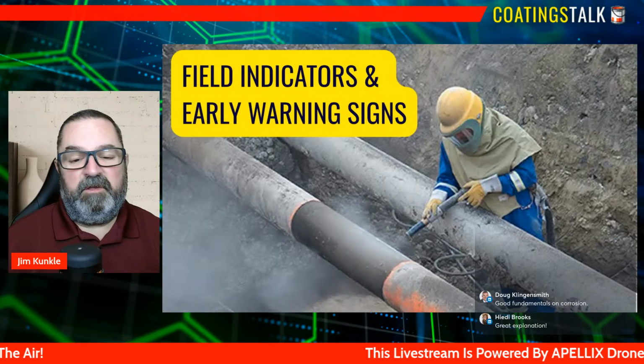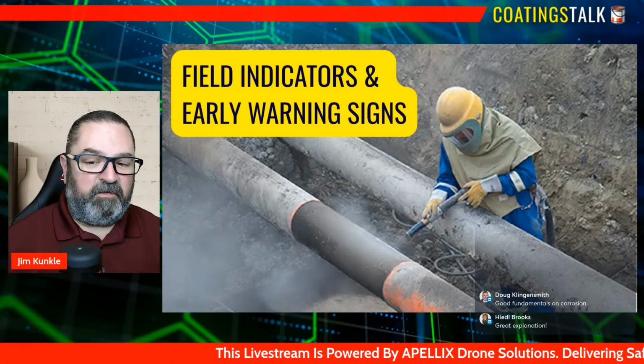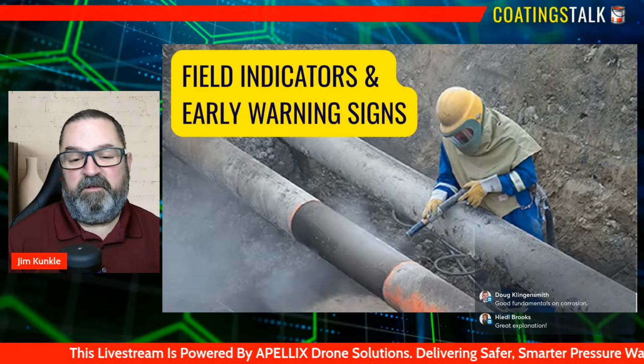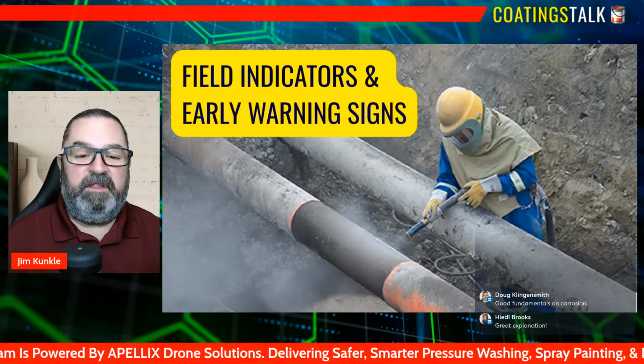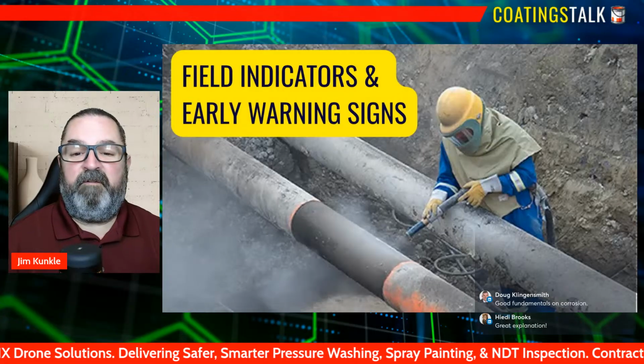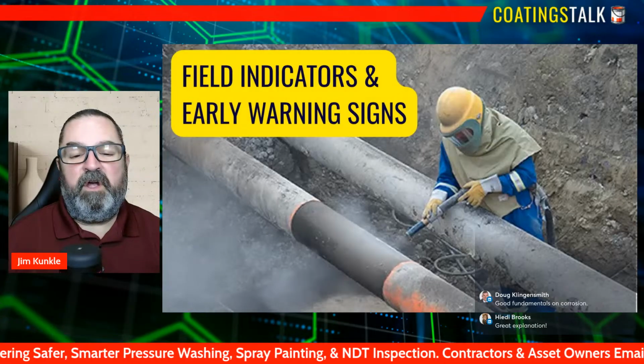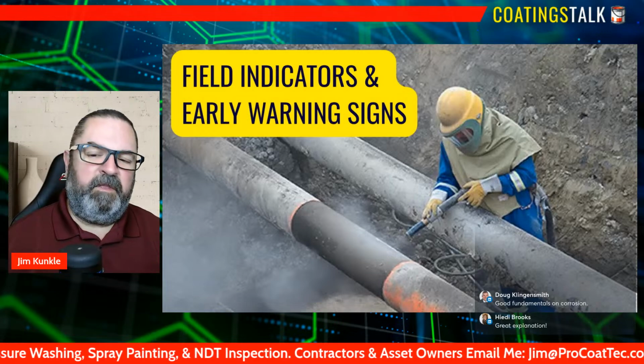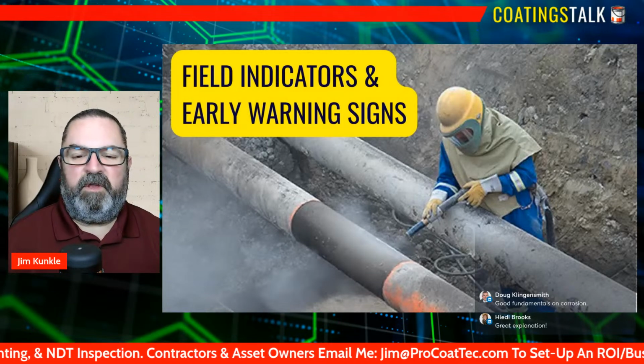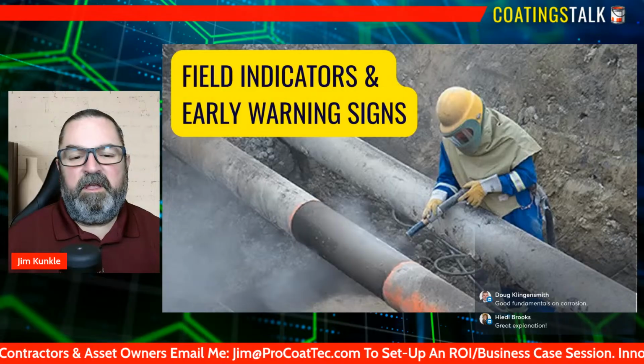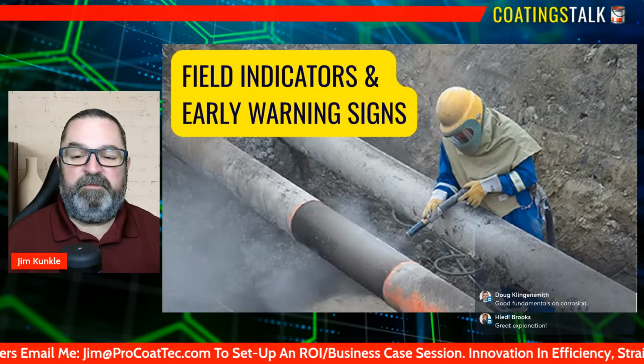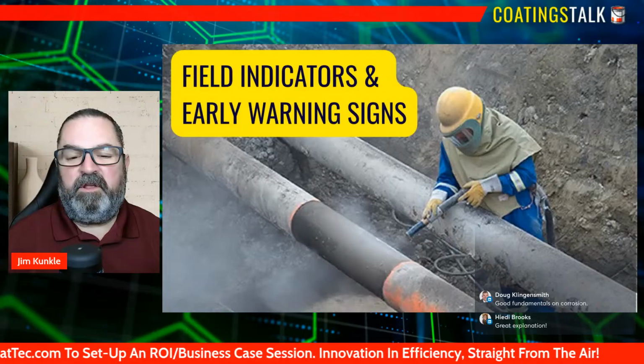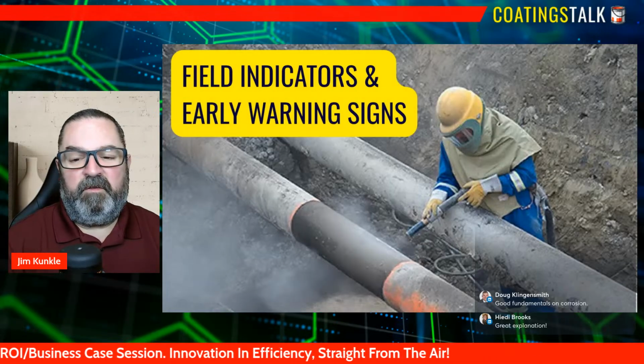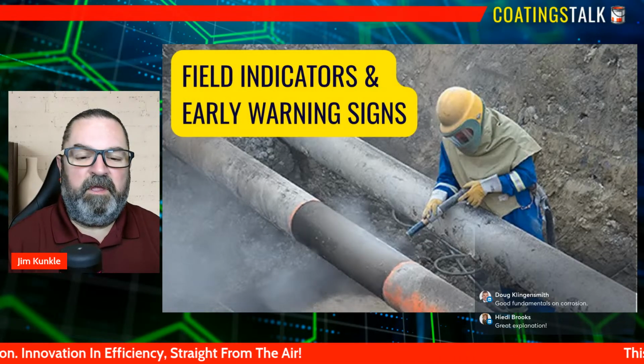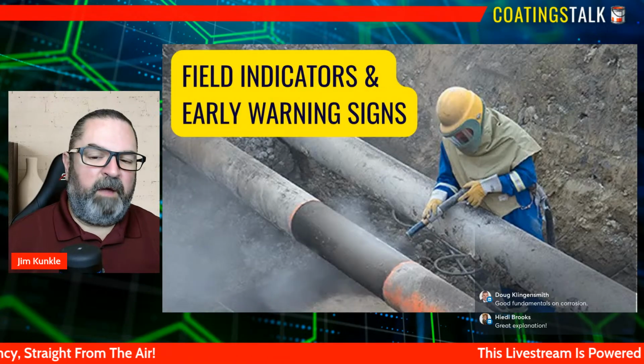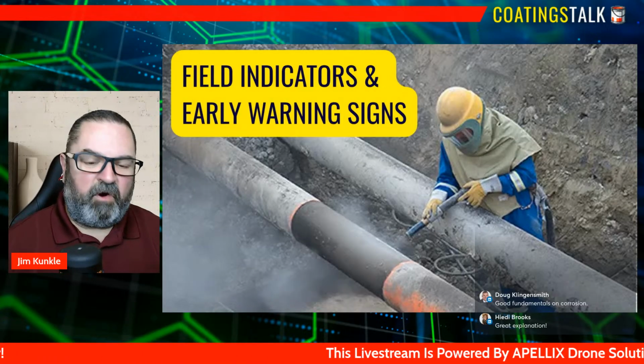Inspectors and applicators should also pay close attention to subtle surface changes that often signal the beginning of corrosion activity. These include discoloration, dulling of the coating, small rust blooms, or areas where the surface texture feels rougher than the surrounding metal. Even minor blistering, pinholes, or hairline cracks in the coating can indicate moisture intrusion or underfilm corrosion beginning to take hold. These early cues are easily overlooked during fast-paced field work, but they are sometimes the most reliable indicators that the corrosion process has already started.